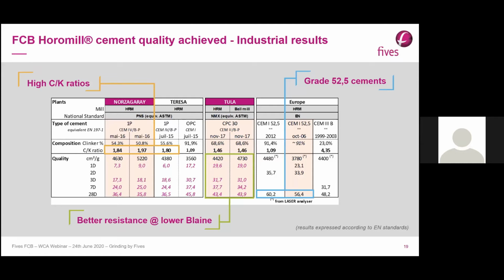On the right side, you just have for information some quality results of high resistance cement or European cement with 52.5 megapascal strength at 28 days. And to the left side, these well-known now Philippine plants of Norzagaray and Teresa with high C/K ratios.